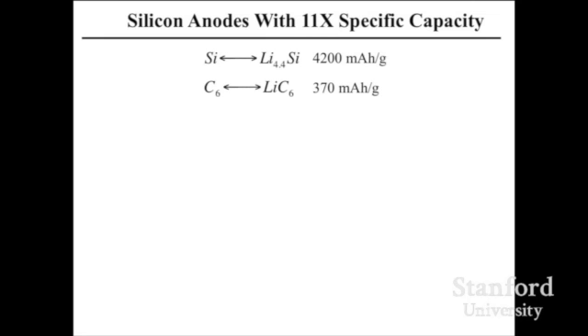Now you start to learn silicon is not only a semiconductor, it's also a great host for a lot of lithium ions. One silicon atom can take 4.4 lithium. In your cell phone, with graphite carbon, 6 carbon atoms take 1 lithium. This produces 11 times the capacity compared to carbon. So why don't we use silicon?